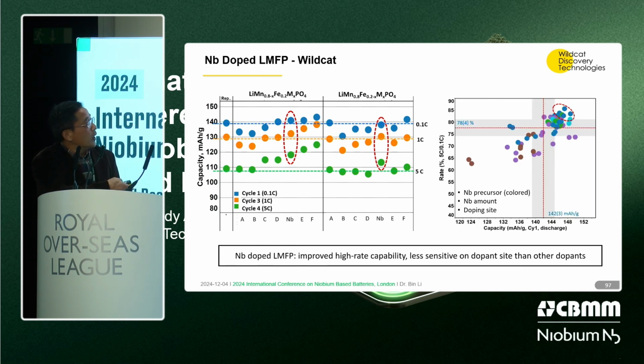So here just shows the doping element. Actually, when we do the experiment, I said we do high throughput screening. You can do many experiments in parallel. What we do is change all of those variables because we know everything that matters. Different precursors will affect, and definitely niobium amount, and also we show the doping site. Here we show the data showing the cycle 1 capacity and the 5C capacity retention. The color shows different niobium precursors. So with each color, you might have different niobium doping amount or different synthesis condition.